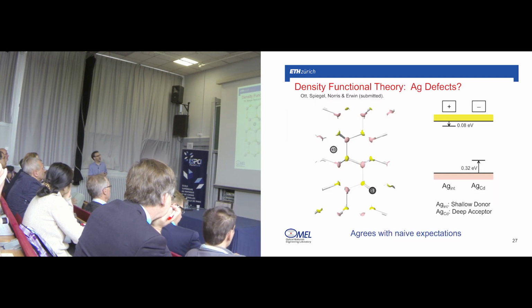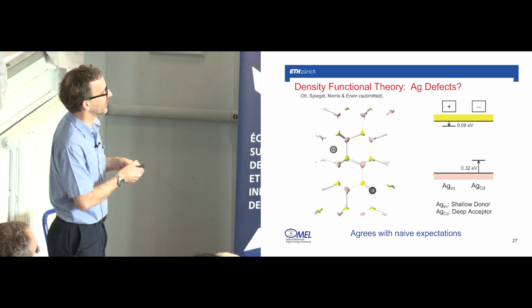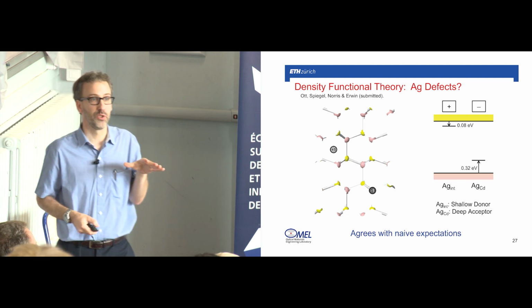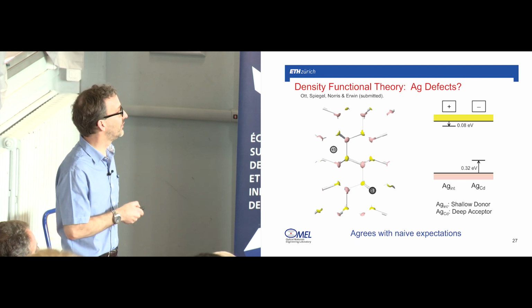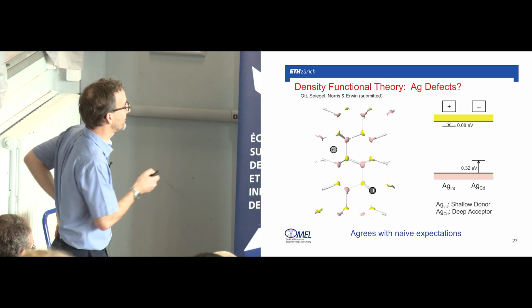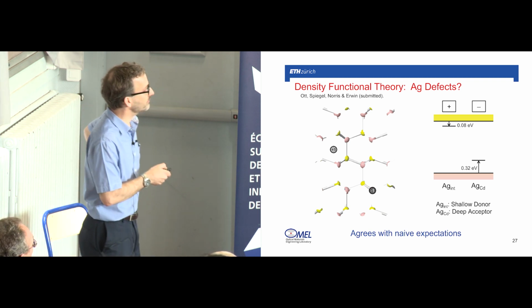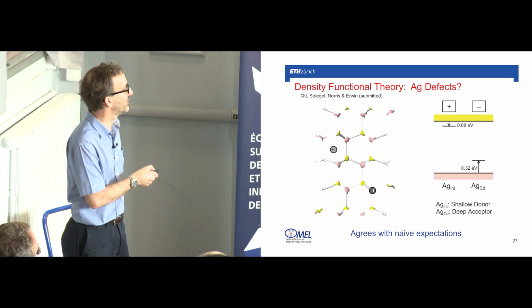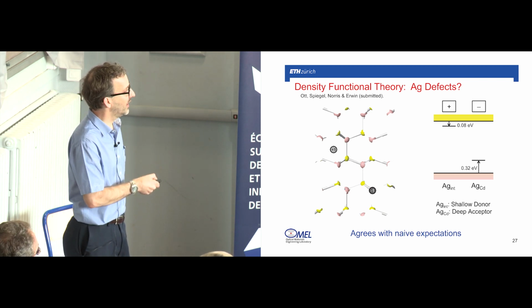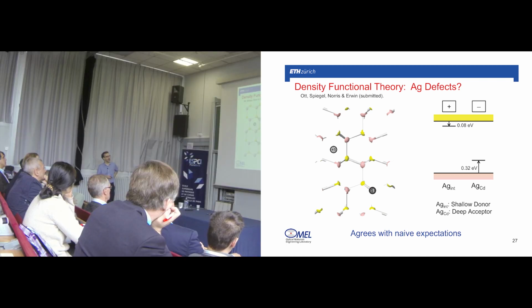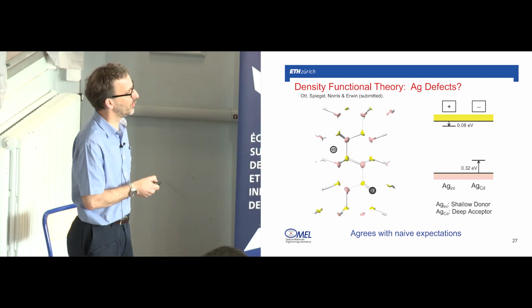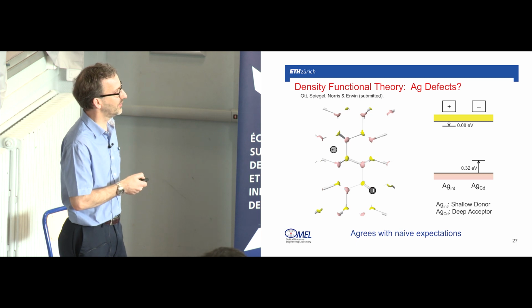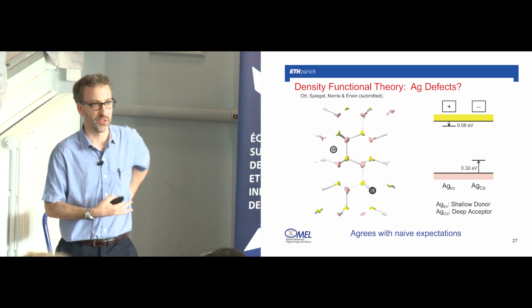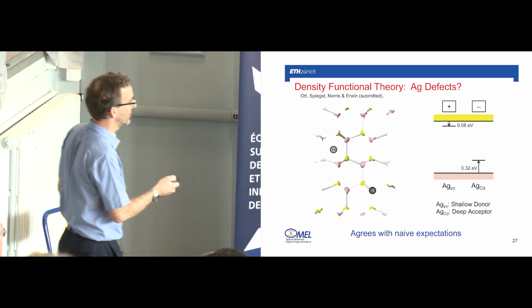And so to get at this, I have a PhD student, Florian Ott, who's working with Erwin, and he started doing density functional theory calculations for silver defects in cadmium selenide. And there are two defects, like I said before, that we have to consider: the interstitial and the substitutional. And the calculations show that an interstitial is a shallow donor. And so if the Fermi level is somewhere mid-gap, then that electron will fall to the Fermi level, and this interstitial will become positively charged. That's what the calculation showed.